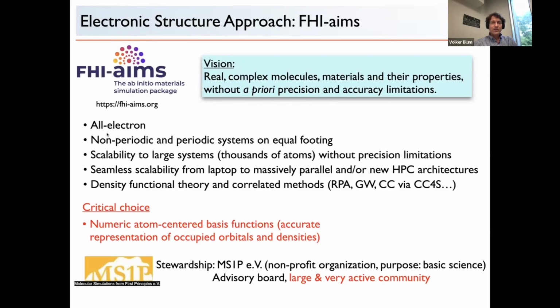The premise was that we wanted an all-electron code, and that is because we knew this could be done, and particularly with numeric atom-centered basis functions, which are the numerical discretization underneath. We knew that this should be possible with high precision, but without losing efficiency. We wanted non-periodic and periodic systems on equal footing, and we do need computers. So we are quite grateful to the people who make working computers because we use them. And so we want to be able to scale to large systems. Often the reasonable limit for first principles that we find is thousands or maybe 10,000 of atoms. But that is what we actually need, it turns out.